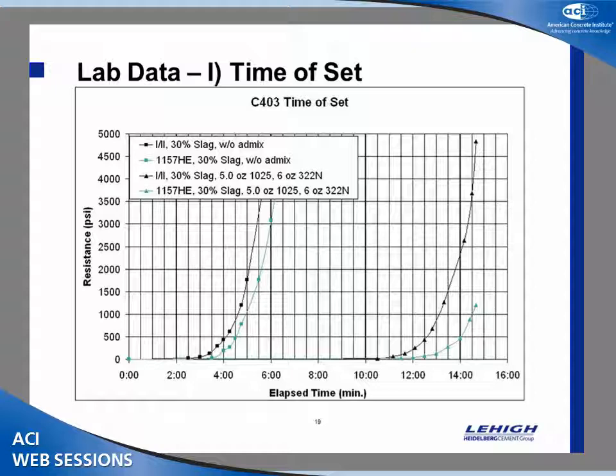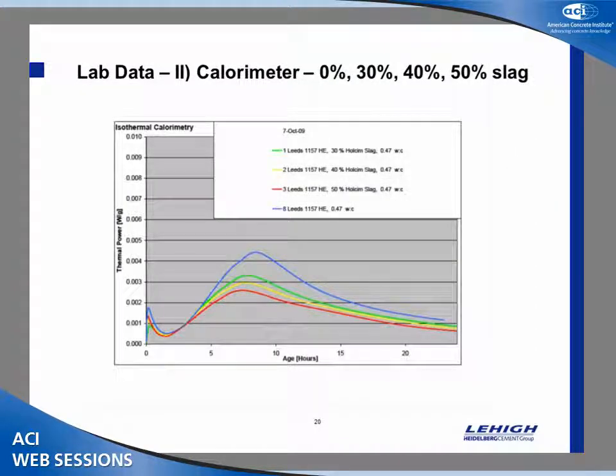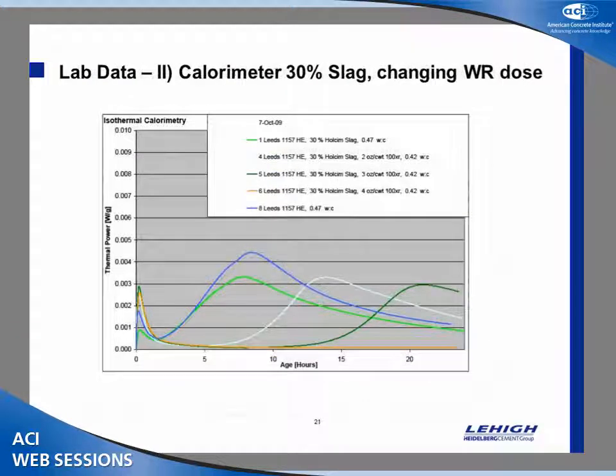So we did a lot of testing, and I'll run through this. Here we have our Portland-limestone cements, and then we have our slags, and then we did an awful lot of testing with different admixtures. What we came up with is that we could alter the set times of this mix quite a bit by the use of admixture and the use of slag. We did calorimetry to look at this data. We studied this thing to death. We did lots of studies here with different amounts. Here's 30% slag.